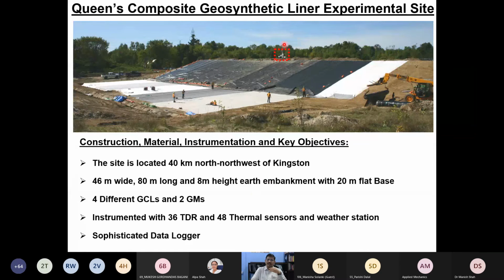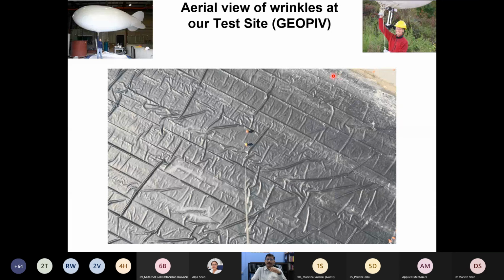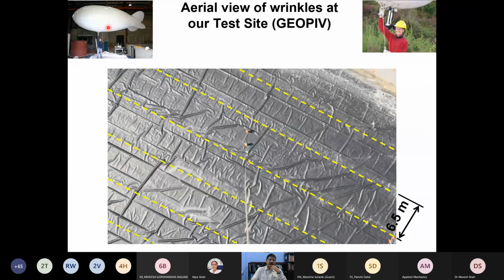So we have a sophisticated instrumentation tool here, and you can see in the first slide, at this particular site, we did quite a lot of experiments, not only on the performance of the geomembrane from an aging point of view, but also how the wrinkles of a geomembrane are going to be addressed. In order to address the geomembrane wrinkles, we filled a balloon with helium gas, and we attached a camera to this helium-filled balloon by using a remote control, and we let the balloon go up almost 60 meters. You can look at these 2 PhD students who did this work, and in the images taken from 60 meters above, they look like a dot. But basically we captured the entire wrinkles by using a digital image analysis processing technique.